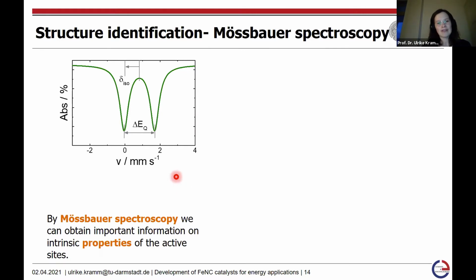And what we have in a Mössbauer spectrum is that we plot our Mössbauer site. In this case, this is, for instance, a doublet with a velocity axis as the x-axis and the absorption as the y-axis. And basically, the x-axis is related to the energy, and the absorption is basically a measure for the intensity. These doublets are characterized by two parameters, that is the quadrupole splitting and the isomer shift.